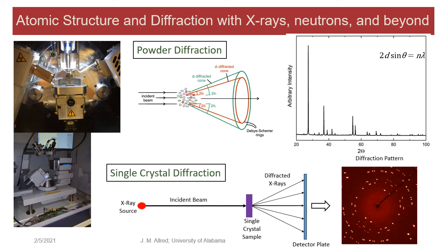Okay, let's say you successfully made something. Now you've got to see what it is you made. Powder diffraction is a great way to do that. You have X-rays and you use Bragg's law, and you can scan through all these different little crystallites in a powder, polycrystalline sample, and you can see what's in there. You can sometimes even determine if you made a new thing based on analogy from known things. It's a very powerful way of looking at what you've made and determining what it is.